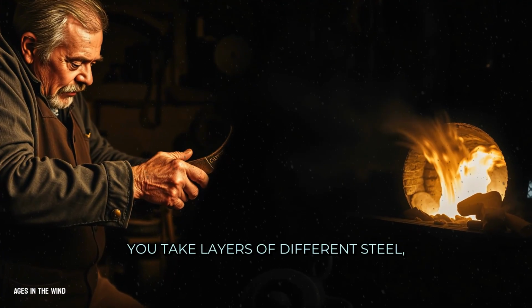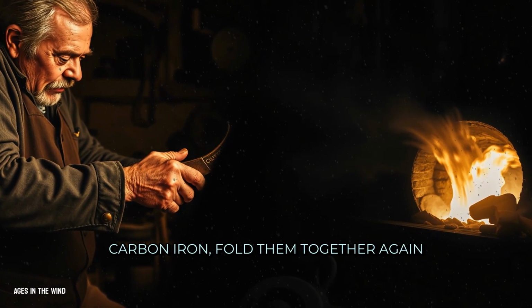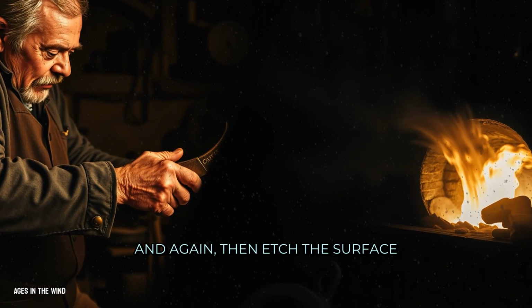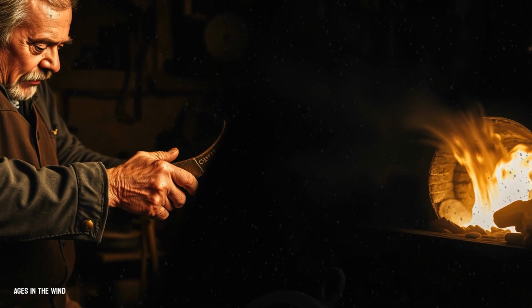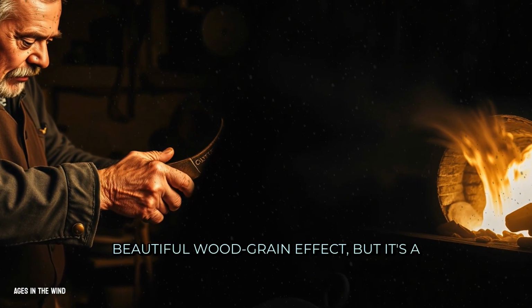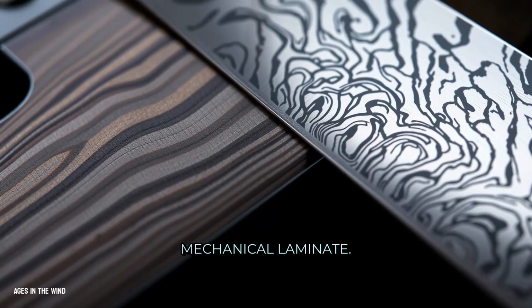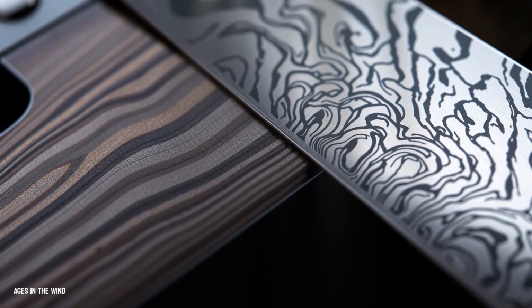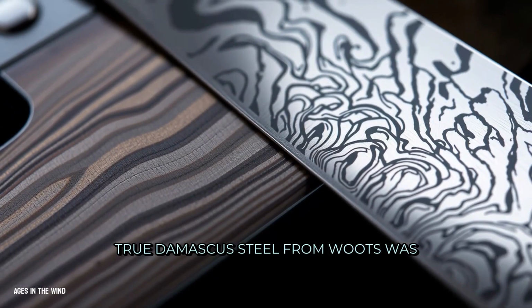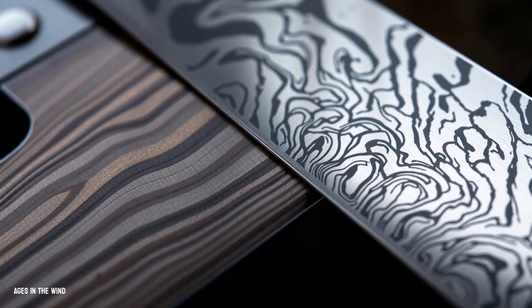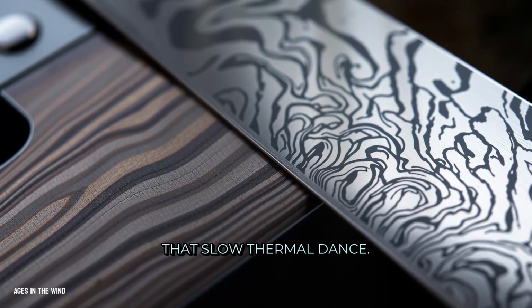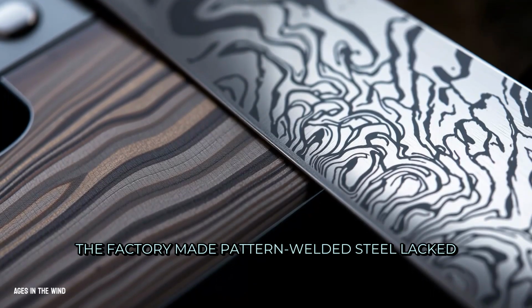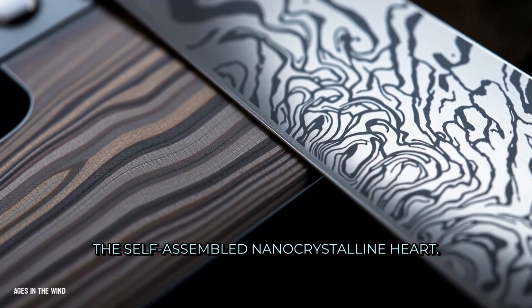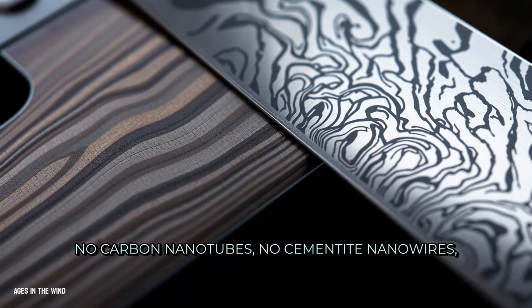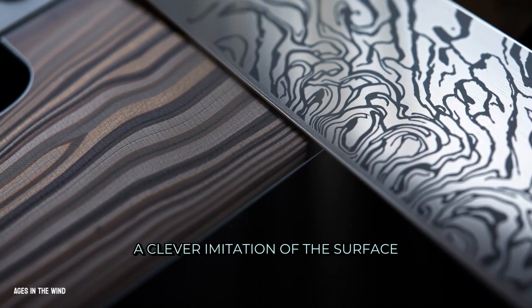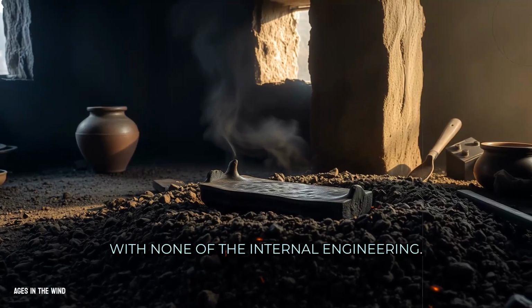You take layers of different steel, a high carbon and a low carbon iron, fold them together again and again, then etch the surface to reveal the pattern. The result can be stunning, a beautiful wood grain effect, but it's a mechanical laminate. It's like making plywood by gluing thin sheets together. True Damascus steel from Wootz was a grown laminate. Its structure formed from within during that slow thermal dance. The factory-made pattern-welded steel lacked the self-assembled nanocrystalline heart. No carbon nanotubes, no cementite nanowires, a clever imitation of the surface with none of the internal engineering.